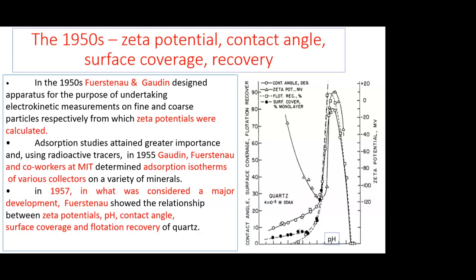The interesting thing about this plot is what has happened in a number of parameters. You'll see if we look at the zeta potential, and the x-axis is pH, the zeta potential starts at somewhere around minus 40 millivolts. And as is traditional, it becomes more and more negative as the pH gets greater. But there's a sudden switchover at around a pH of 8 or 9. And you can see the zeta potential suddenly goes back to about zero. And that's accompanied by two other observations. The first is it coincides approximately with full surface monolayer coverage.